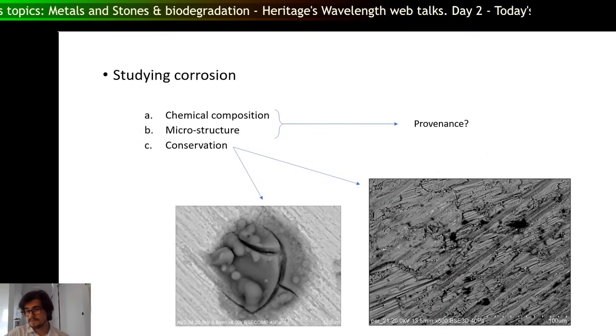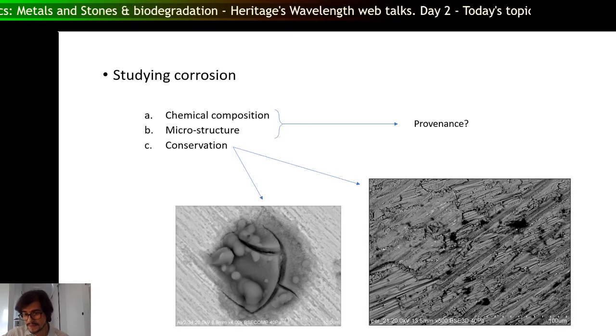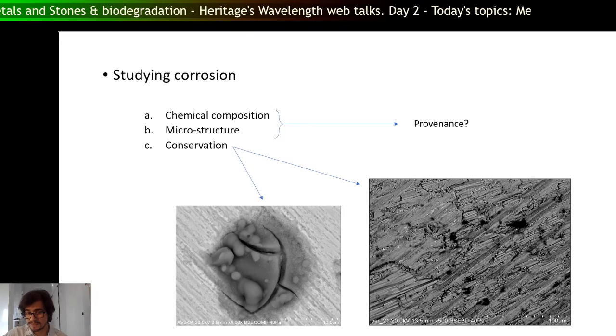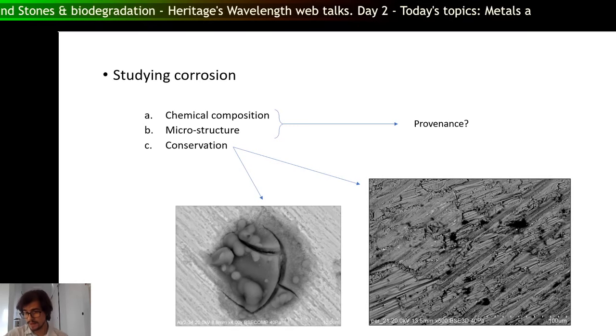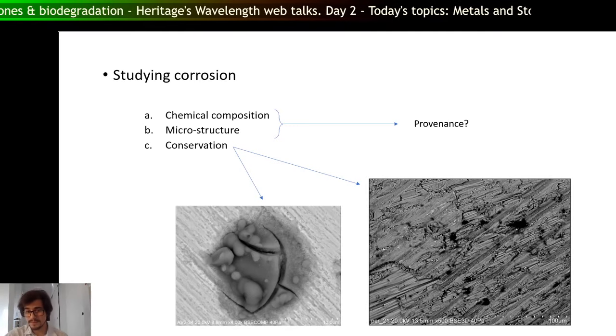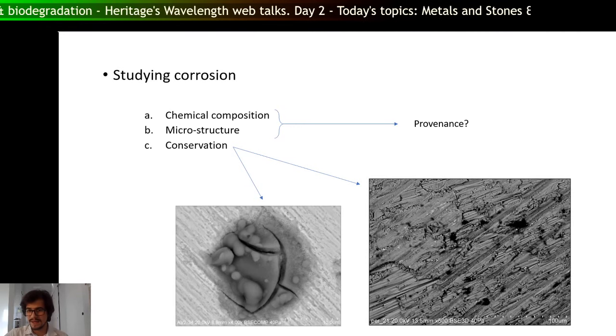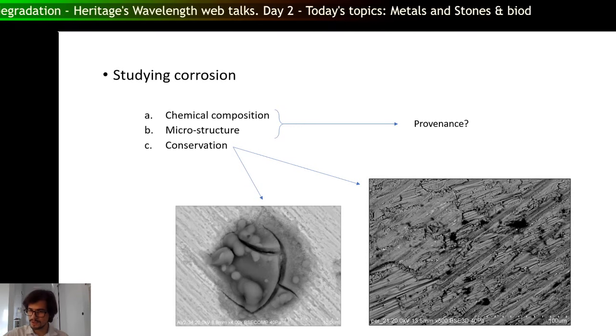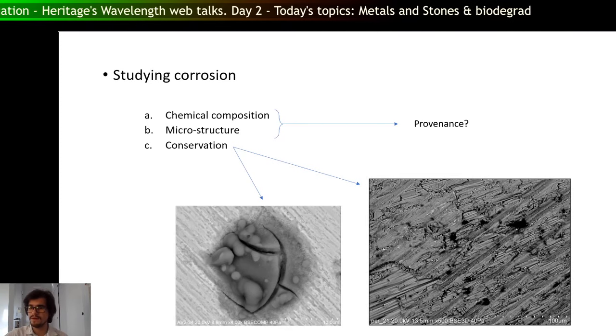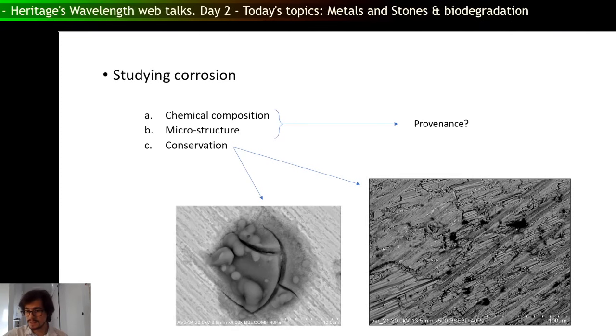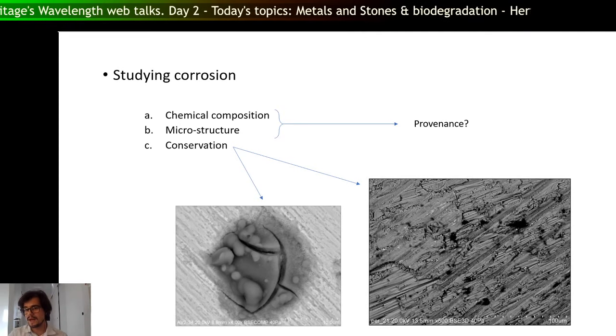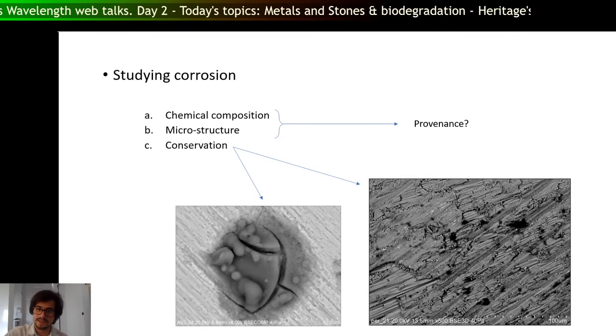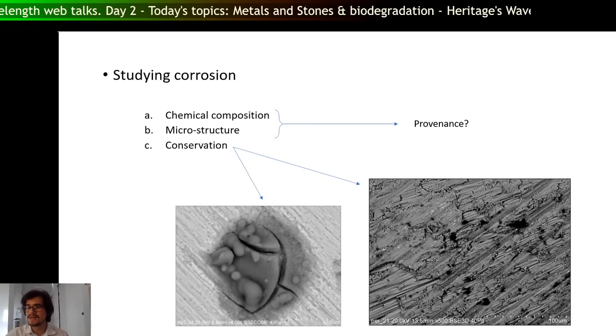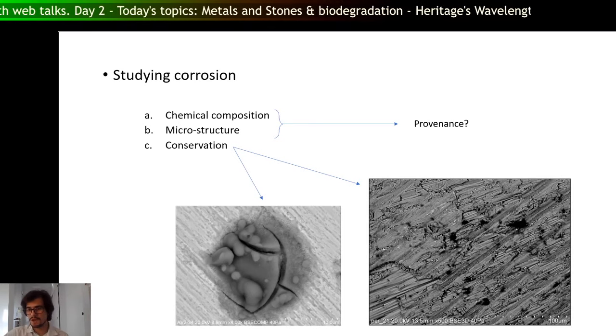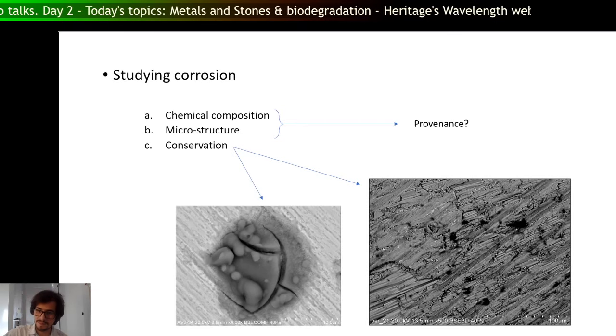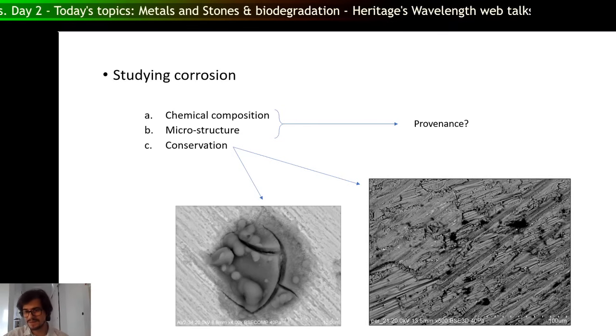Bronze disease is a type of pitting corrosion, and it is a cyclic corrosion mechanism promoted mostly by chlorine. Chlorine is very aggressive to bronzes, and once it cracks that outer noble patina layer and manages to get underneath it, it fuels a cyclic process, creating anions that further react with the environment, that create more chlorine anions that enter the material and create more anions that will react with the environment, and it just goes on. So you can see these black dots spreading throughout the surface of the object.